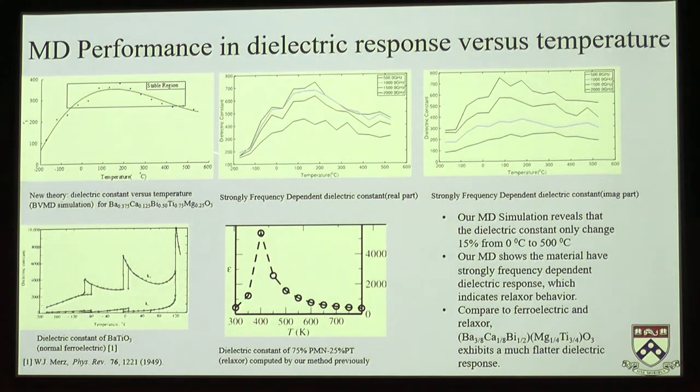And the x-axis of the second figure is the temperature. The y-axis is the dielectric constant. This is the real part of the dielectric constant. You will see that as you increase the frequency, the dielectric constant decreases. This agrees with the theory.